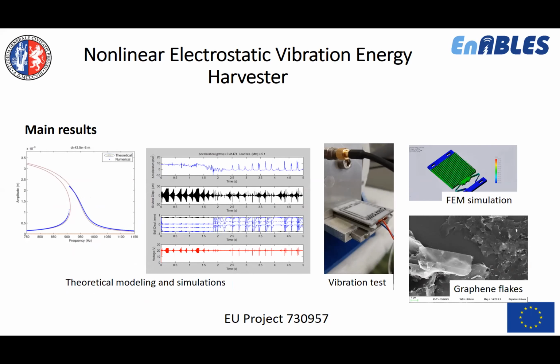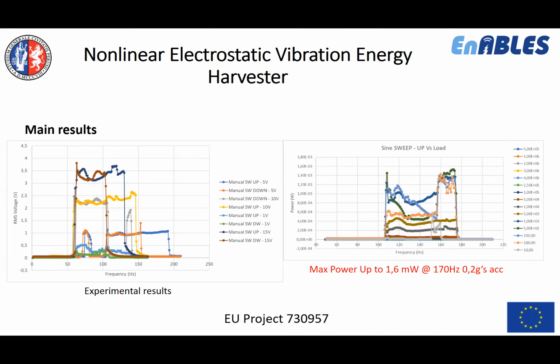And on the next slide, some electrical results measured on this kind of components. And you can see that some maximum power of 1.6 milliwatts was achieved at a frequency of 170 hertz and with an acceleration of 0.2 g, which is quite notable for such a component. So that was the first highlight dedicated to the energy harvesting part.